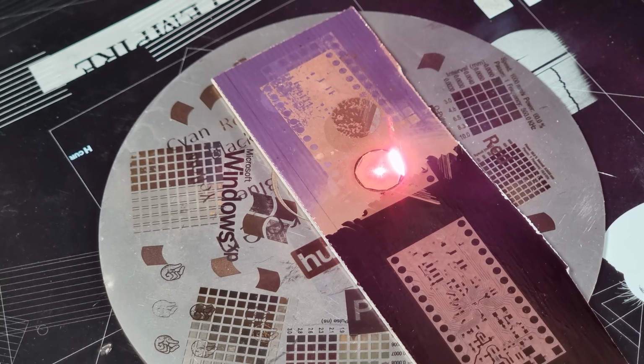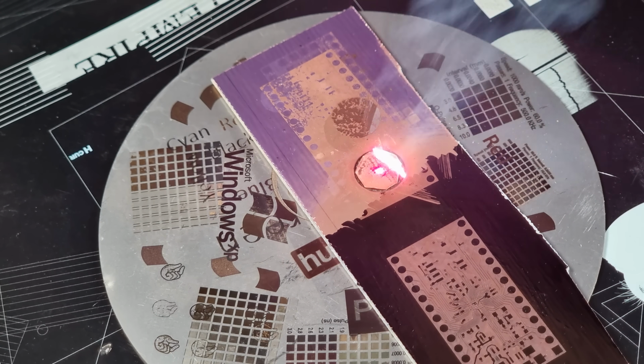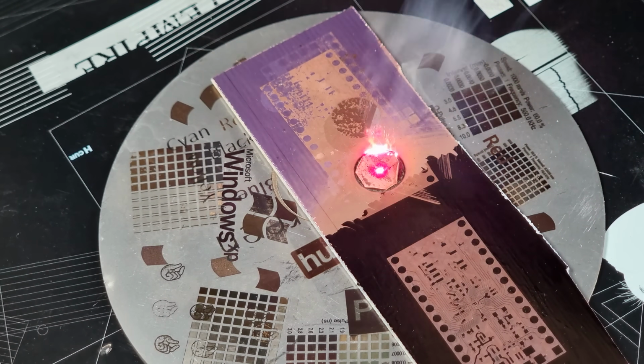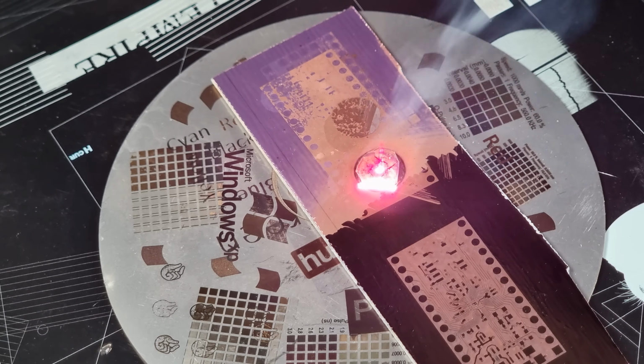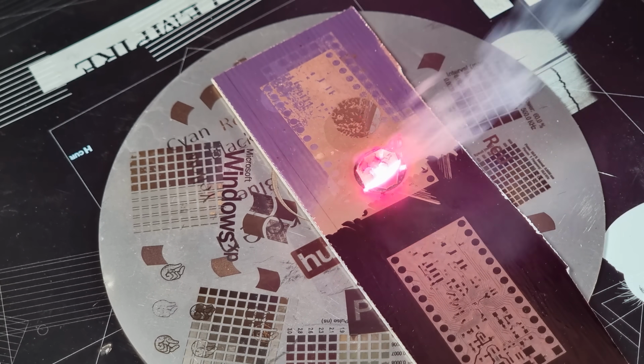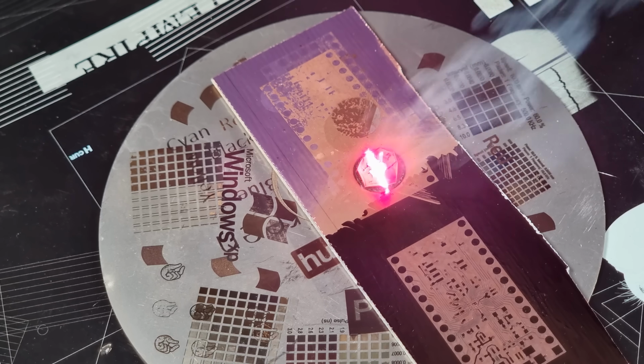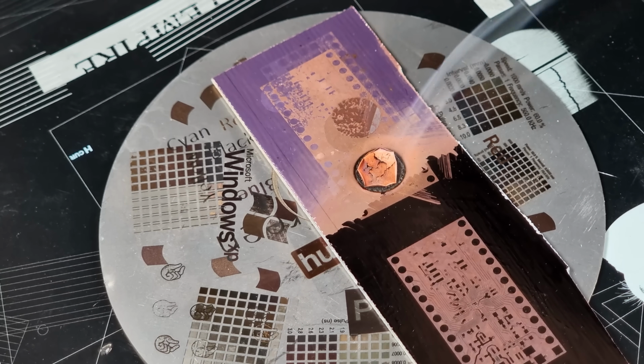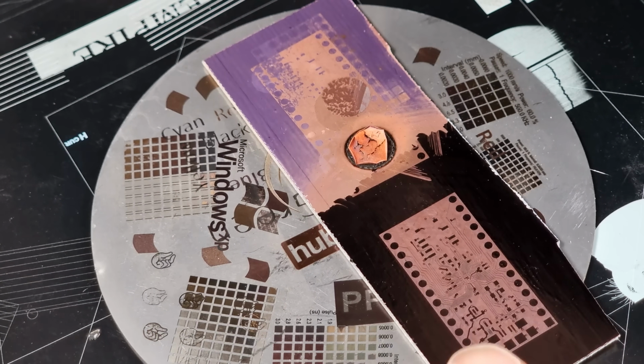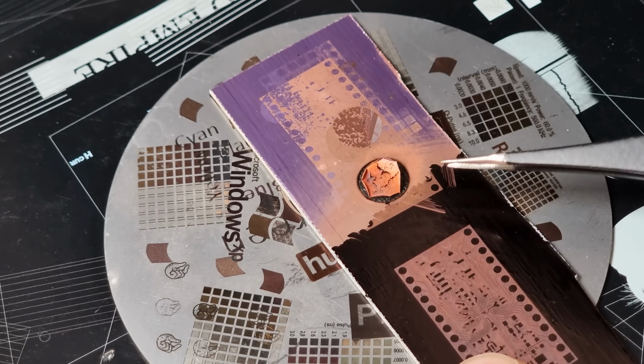But as before, this wouldn't be my first choice for PCB prototyping, only in the most dire circumstances. The smallest features tend to get scorched and delaminated unless you go really slowly, and the substrate below gets a nice conductive black sear, except if you get perfectly uniform material removal and are able to stop the process instantly when the copper is gone. Those are the usual process limitations. Technically, this machine will definitely structure circuit boards for you.